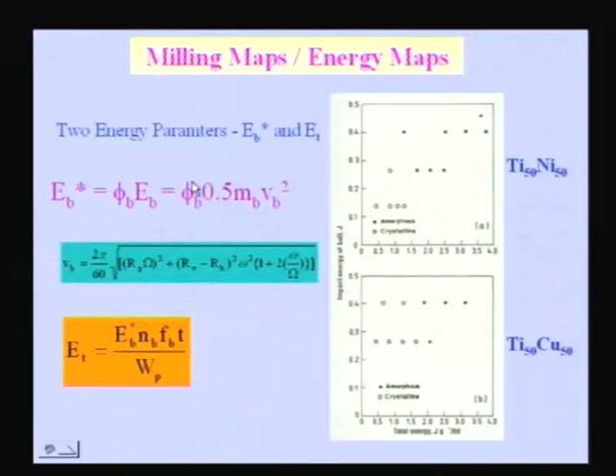So if we know the mass of the ball and the velocity of the ball, one can calculate half mv square. In addition, one has to consider ball to ball impacts, because some energy is lost when a ball hits another ball. So the effective energy transferred from the ball to the powder is decreased. Because of this, we multiply with a parameter called phi b, which decreases the overall impact energy of the ball. So this EB star is nothing but the effective impact energy of the ball, and one can calculate phi b very easily depending on the extent of filling of the container, the ball to powder weight ratio and things like that. And the total energy of the ball is crucial.